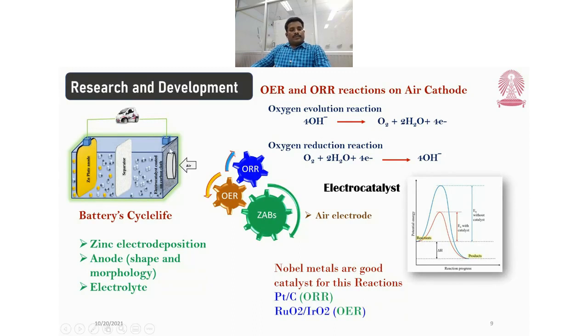On the other side, at the air cathode, two major reactions limit the efficiency and cycle life of the battery: the oxygen evolution reaction and the oxygen reduction reaction. In the evolution reaction, hydroxide ions are converted into oxygen molecules. In the reduction reaction, oxygen molecules are converted back into hydroxide anions. To increase the efficiency, we can put some catalyst on it, which can increase the reaction rate.